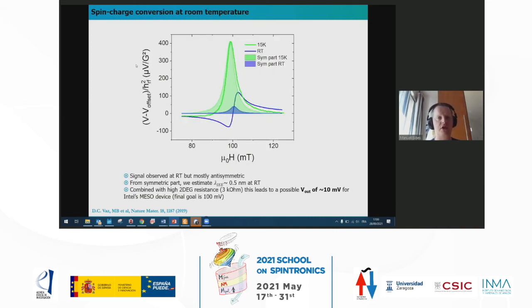This is a result of spin charge conversion with the same system at room temperature. So the effect is much smaller, but still, if you remember, I told you that we need an output voltage of 100 millivolts with the MESO device. With this figure of merit that we extracted, we can in principle reach maybe 10 millivolts. So we are not quite there yet, but this is still quite encouraging.